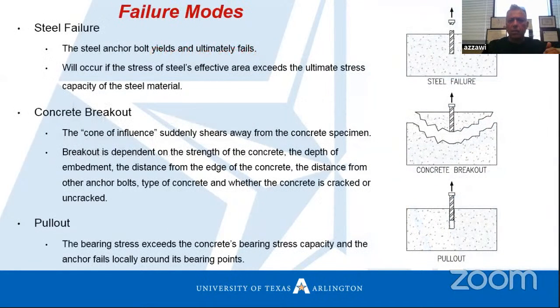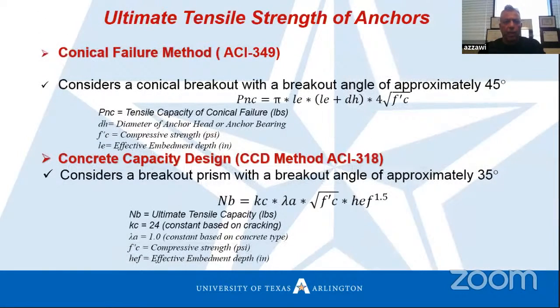In fact, we used polypropylene fibers here, not steel fibers, just to see what is the difference between steel and synthetic fibers. This slide shows us the failure modes we expect with an anchor bolt. For any anchor bolt in tension, we expect either steel failure, where the anchor bolt itself fails by yielding if we have good anchorage between anchor bolt and concrete, or concrete breakout failure, and this is the common failure we have in industry. The other one is pull out, if we don't have enough bond, enough anchorage, enough development length for this anchor. The most common failure, as I mentioned, is the second one, which is concrete breakout.